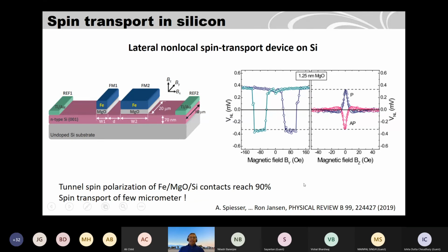And in silicon, you can also do spin transport. In this paper, it has been shown that if you have a ferromagnet injector and a detector, you can have a channel length, inject spins from here and detect them here, and you can get a very large spin signal. This is the spin valve signal when you have parallel and anti-parallel magnetization. And this is the Hanle spin precession signal for the parallel and anti-parallel case. And the tunnel spin polarization achieved is up to 90%, because an MgO barrier is used here.